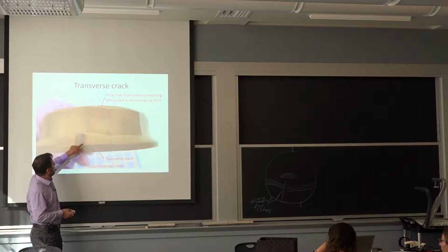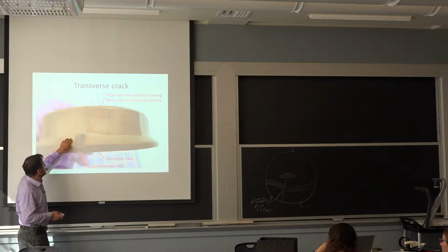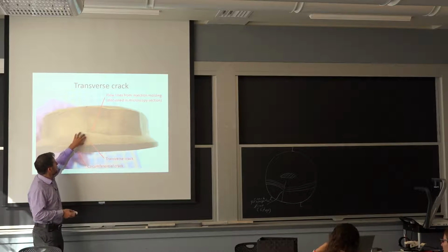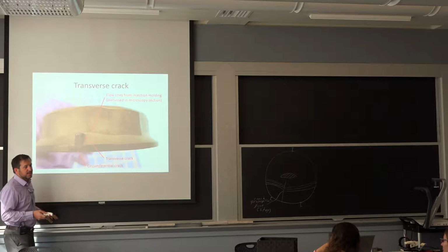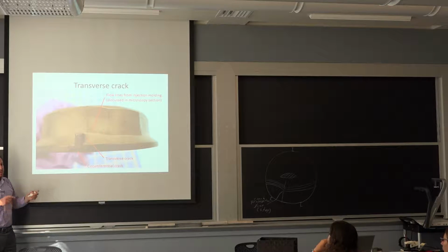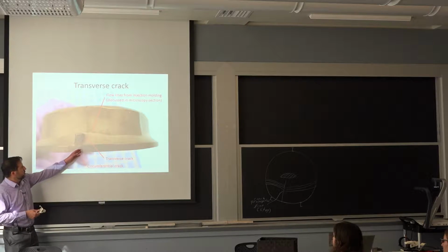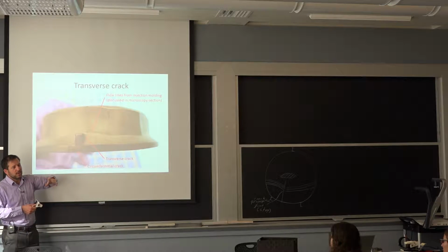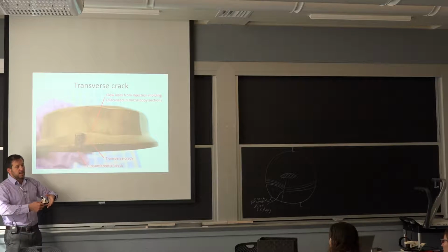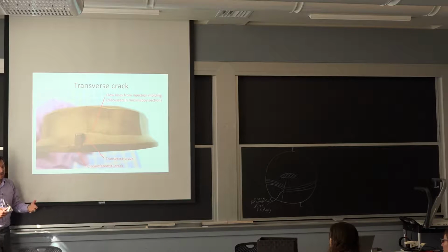Next time I'll bring the part, next time I present this. But you can see that essentially the resin is flowing from this point. So this is not really what we call the mold line between injection points. This is at the injection point. And the only reason why you could initiate here is, first of all, you're in the bigger diameter, so as you torque it up, you get more stresses there, because that nut's going to grow in diameter, so you get more growth on the outside.